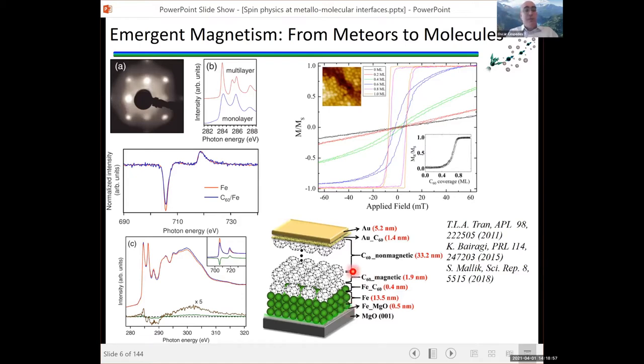And this was used, for example, by Bairagi and colleagues to generate out-of-plane anisotropy in cobalt. So here we have plain cobalt in black, measured out-of-plane in the SQUID. And what you can see is this is the hard axis. So you have a linear slope with a high saturation magnetic field. But as you start to put C60 on top of the cobalt, the thin film slightly starts to become out-of-plane magnetized.